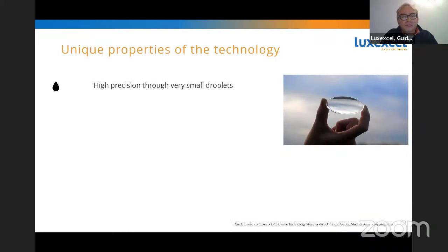So the reason we're so precise is we use very small droplets. The reason we achieve high speed, coming to your point, Ralph, how long does it take? Well, to print a batch of lenses takes, depending on the prescription and some more variables, roughly between half an hour and an hour. So it goes very fast for 3D printing. And that is because we massively parallel deposit these droplets.